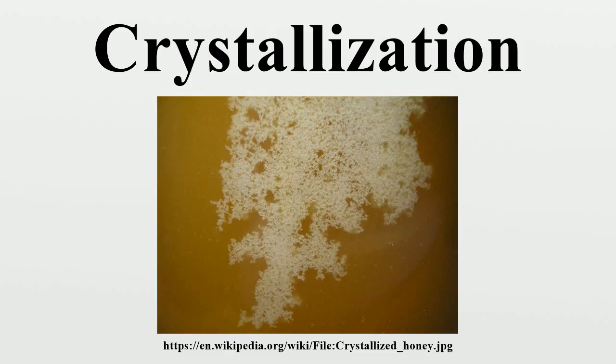The main values to control are therefore supersaturation value, as an index of the quantity of solute available for the growth of the crystal; total crystal surface in unit fluid mass, as an index of the capability of the solute to fix onto the crystal; retention time, as an index of the probability of a molecule of solute to come into contact with an existing crystal; flow pattern, again as an index of the probability of a molecule of solute to come into contact with an existing crystal. The first value is a consequence of the physical characteristics of the solution, while the others define a difference between a well and poorly designed crystallizer.